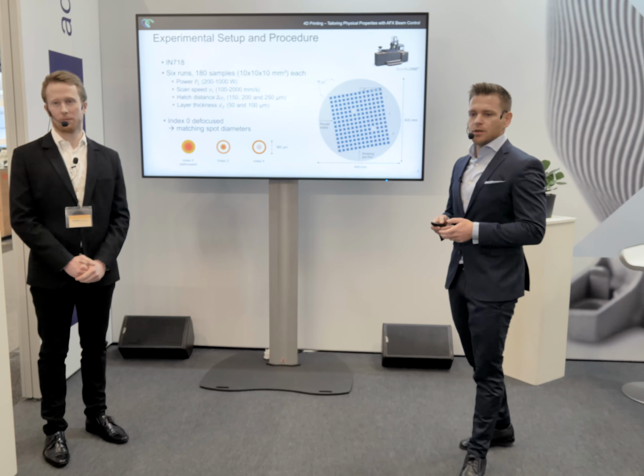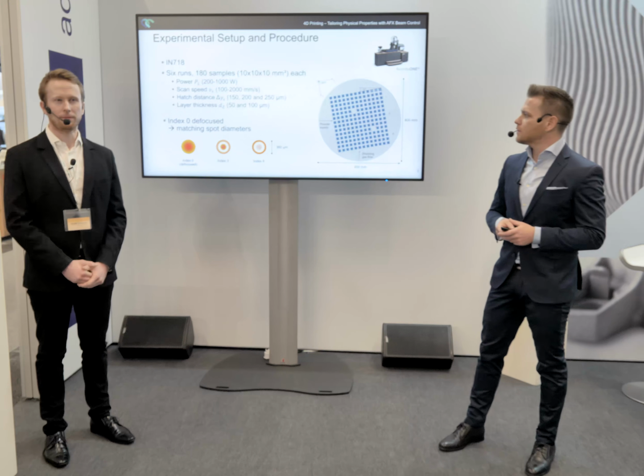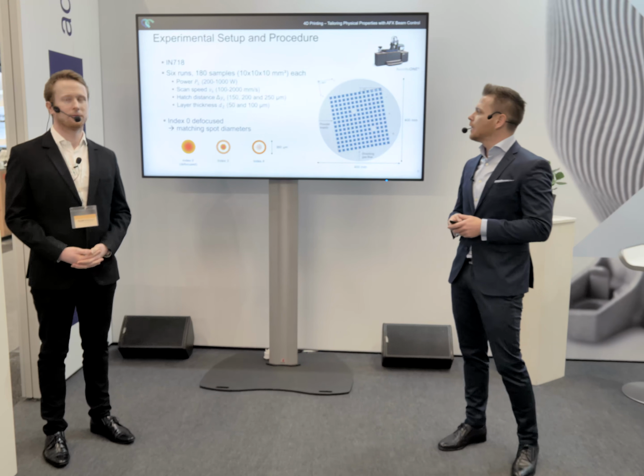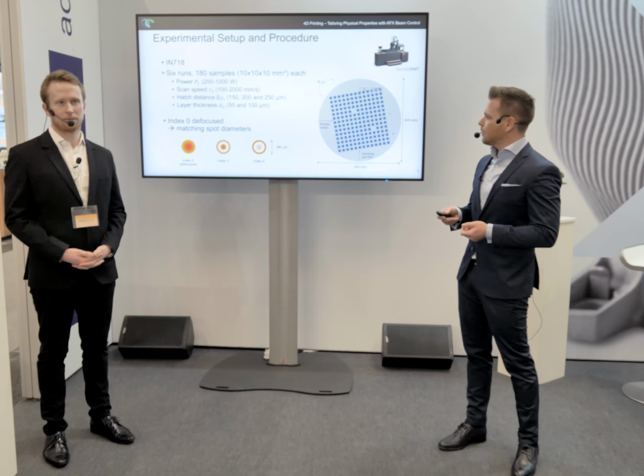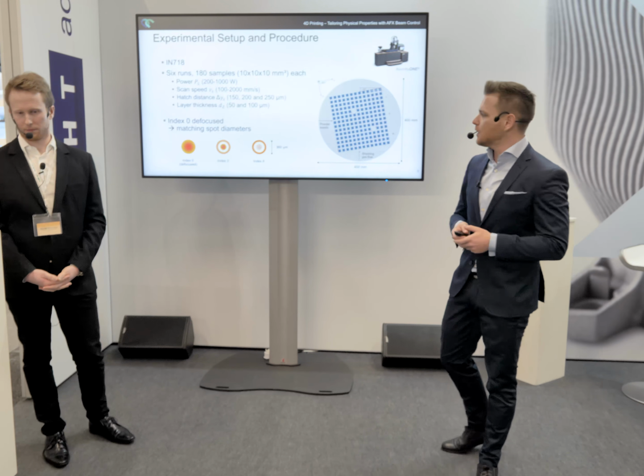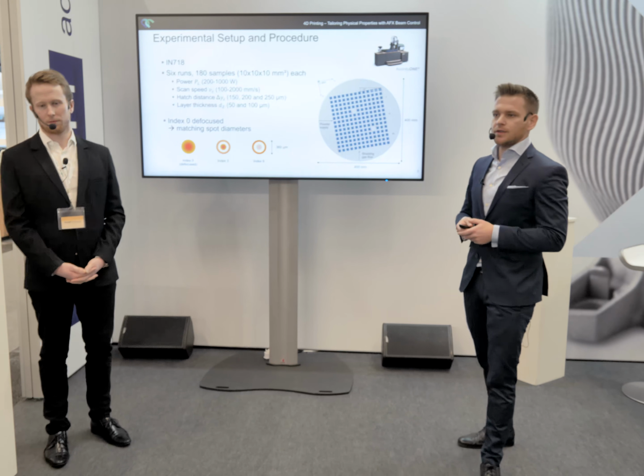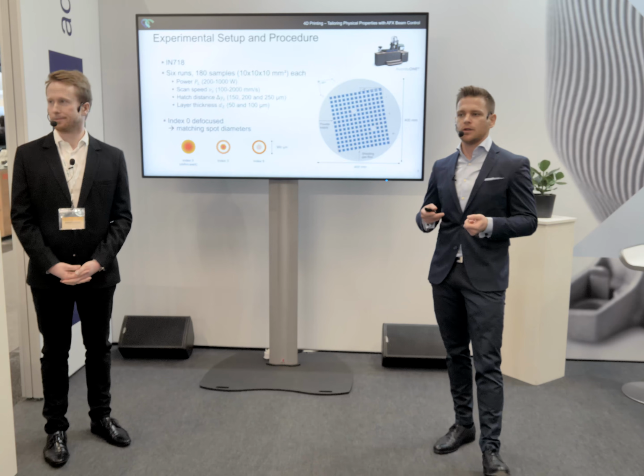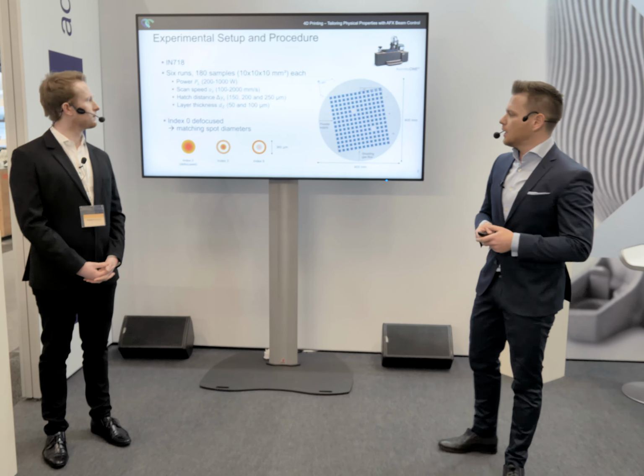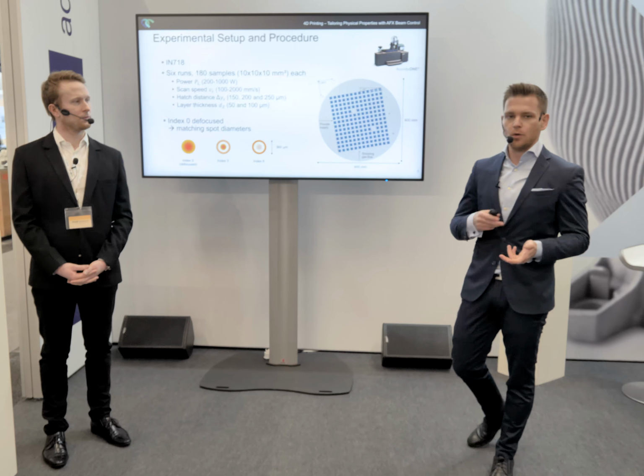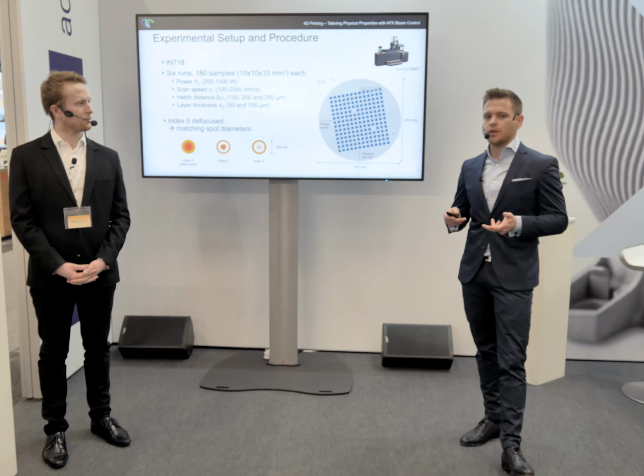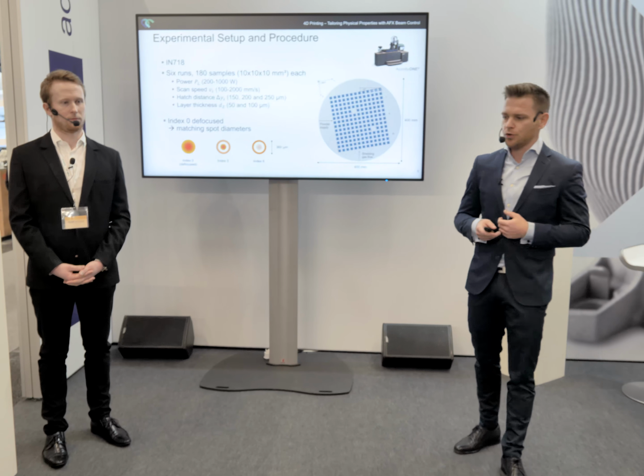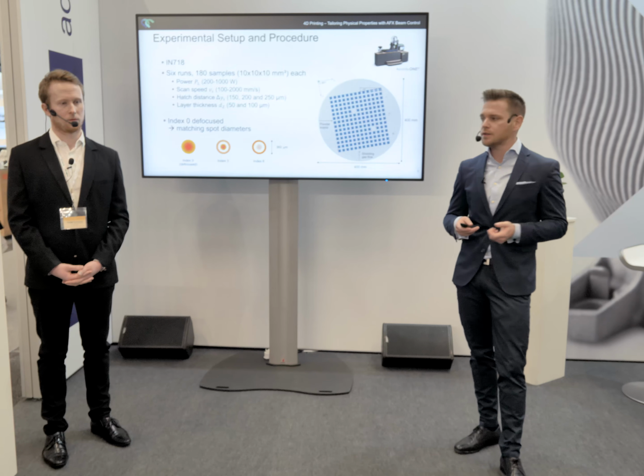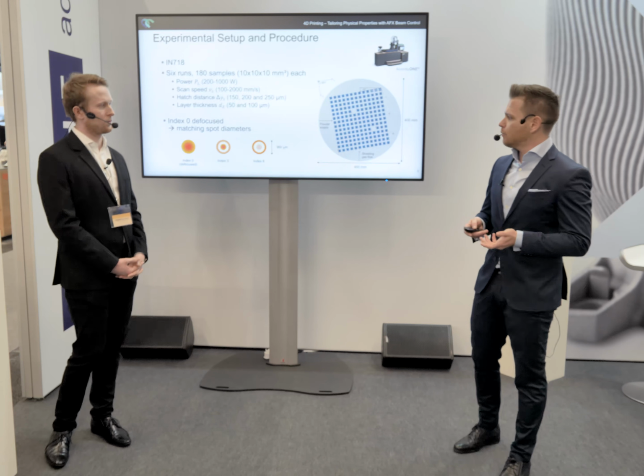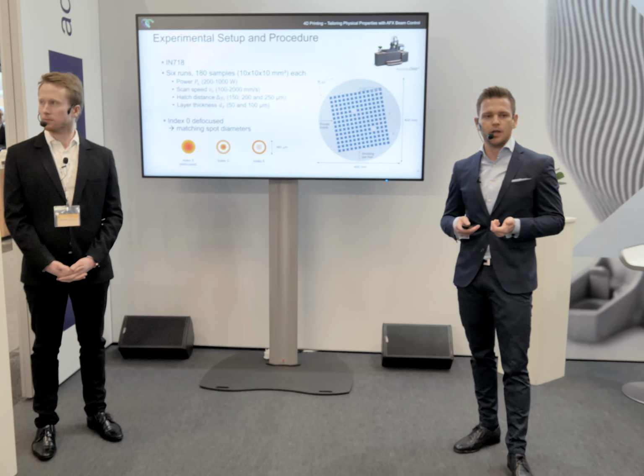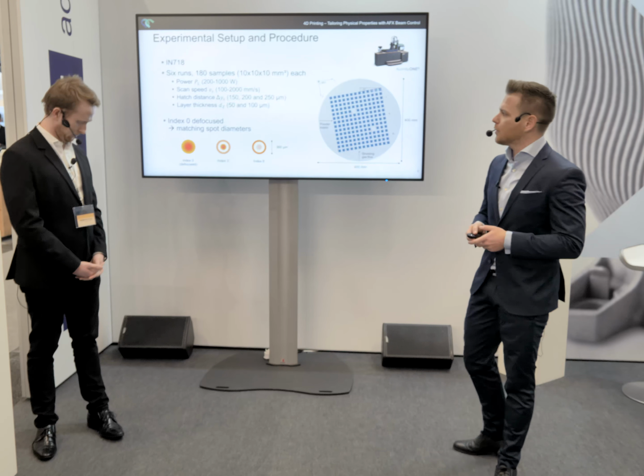To investigate this innovative laser, we set up different experiments, a broad parameter study with the nickel-based superalloy Inconel 718, varying laser power, scan speed, hatch distance, and layer thickness. We chose 3 out of 7 different intensity distributions: index 0 as the representative for the Gaussian beam, index 6 the ring profile, and index 3 as a combination of both. Additionally, we defocused the spot of index 0 just to be sure that there is no other influence of differing spot sizes. Otherwise, constant process conditions enabled us to investigate the isolated influence of the different intensity distributions on the final parts.